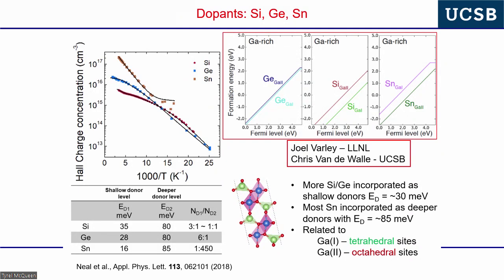And then we can find, and it's very interesting, there are two slopes here, which is a strong hint that there are two donors. And all three of these species actually have two donor sites. We attribute this to the two different gallium sites in this crystal structure. So we have a shallow donor, which is what we call the hydrogenic donor, and a deeper donor, okay? And so far from all of the work, silicon is the most favorable because silicon primarily goes to the shallow donor site, okay?